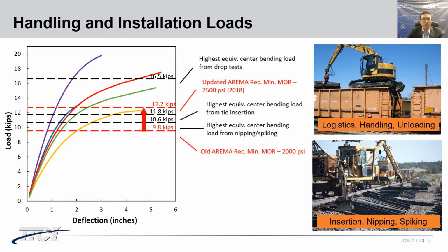First, we explore the loading environment during handling and installation, where the ties could experience a more severe loading condition. We measured the bending stresses in composite ties during a typical installation process and in drop tests to simulate severe loading conditions. Tie remover inserter machine was used for tie installation. Simulated drop test was from 4 feet high.